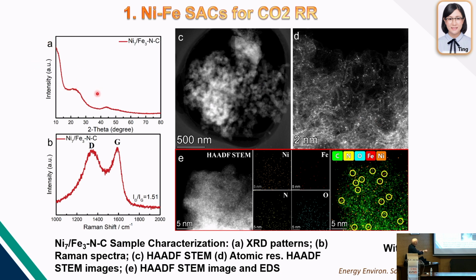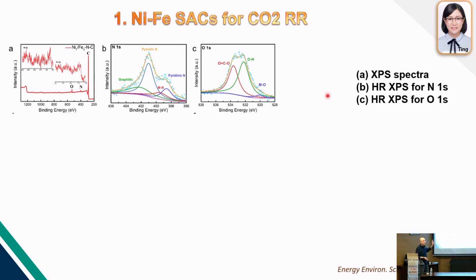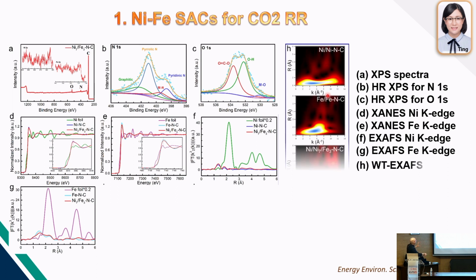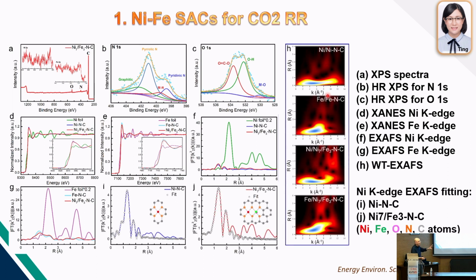Here we can see slightly the peaks of the graphite, graphene-like structure, but we cannot determine if these are really atoms of nickel and iron. So what we need to do is going to XPS, but even further, going to the synchrotron. And here, you can more or less determine the coordination of your atoms. Is it true? You see that all the peaks are not really adapting closer or exactly in the position that you are simulating. But if you combine this with the TEM in which you are seeing the atoms, you can get an agreement in which more or less, not all of them, but most of the atoms will be in this position, okay? Getting this type of coordination and bonding.